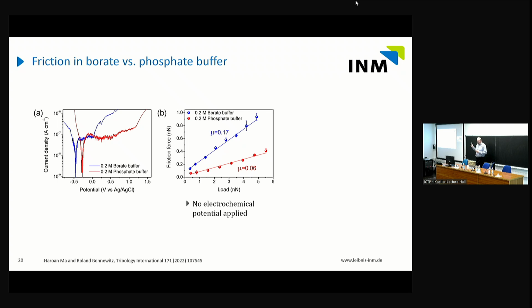But borate buffer and phosphate buffer worked, and these are a little bit different in how aggressive they are. And we found that by simply immersing our metallic glass into these two buffers, we got different friction on the same metallic glass. So just immersion led to different friction coefficients, and so how's that?